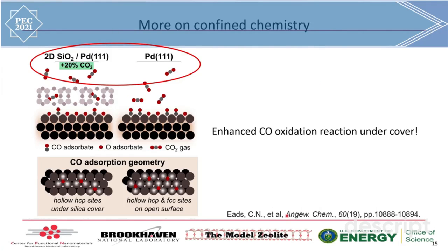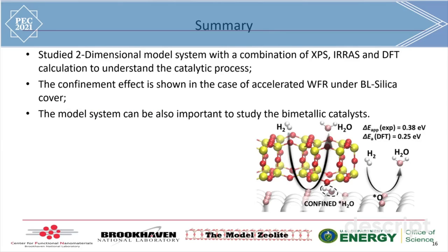And one of my colleagues also found that, similar to the water formation reaction, the CO oxidation reaction is also enhanced by almost 20% under the silica bilayer supported on palladium 111 compared with a bare palladium surface. So in summary, we studied a two-dimensional model system with a combination of various surface science approaches and the DFT calculation to better understand the catalytic process. And the confinement effect is shown in the case of accelerated water formation reaction under the bilayer silica cover.